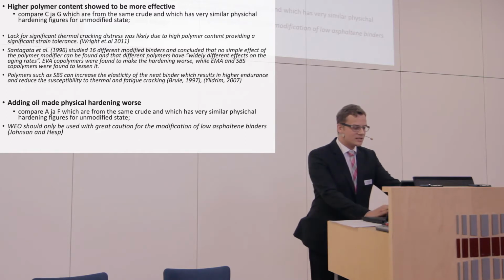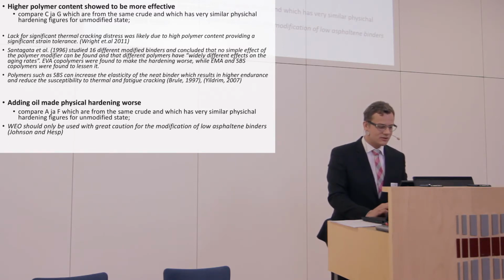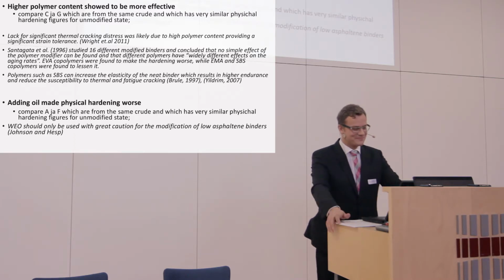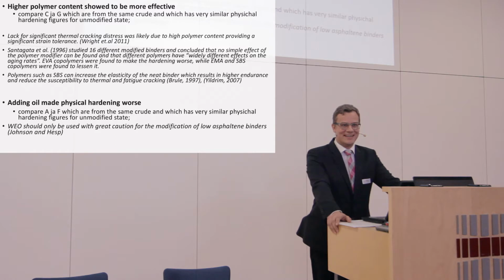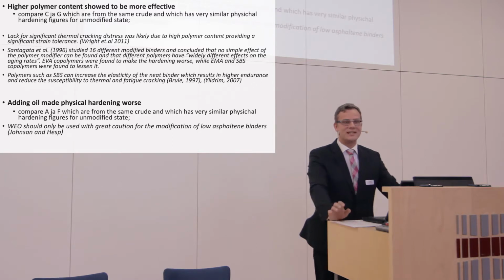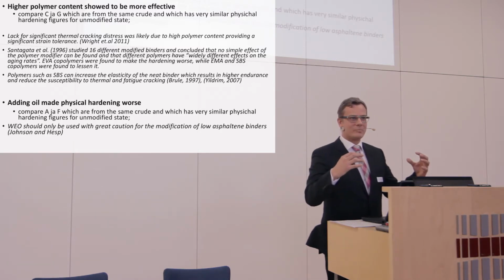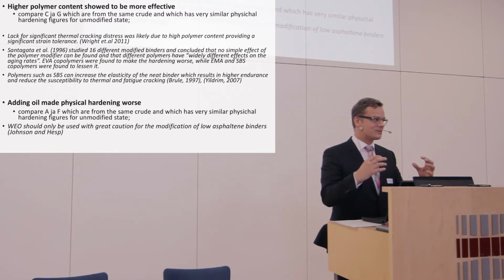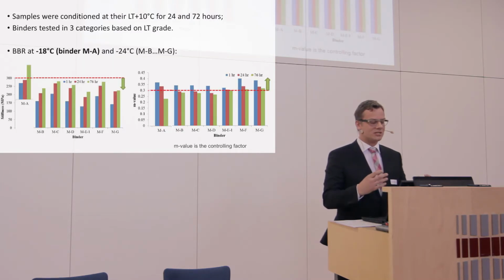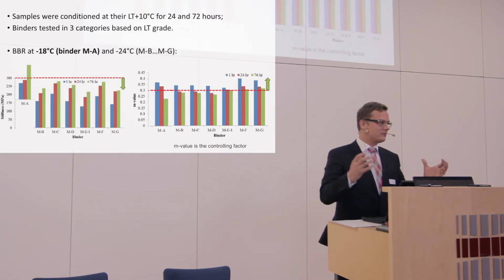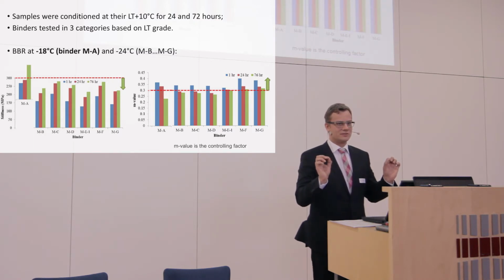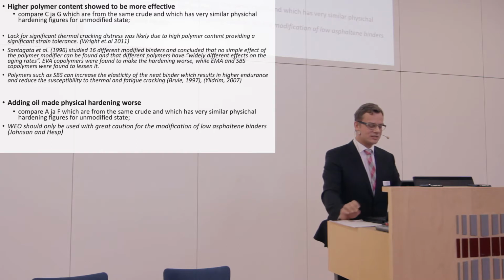Also, polymers such as SBS can increase the elasticity of the neat binder, which results in higher endurance and reduced susceptibility to thermal and fatigue cracking. So in the literature we can see that SBS helps a little bit to withstand reversible hardening, and we can see from our results that this is true. We have only 2 comparable points, but here we can see the results.